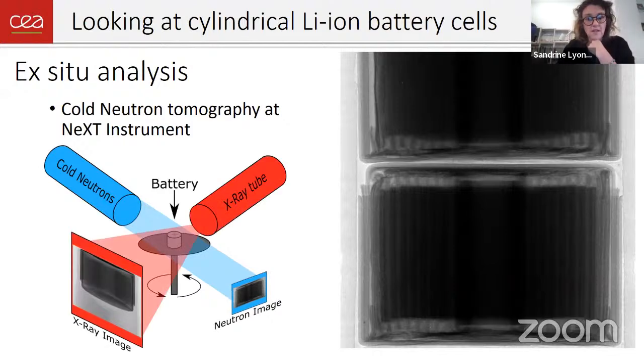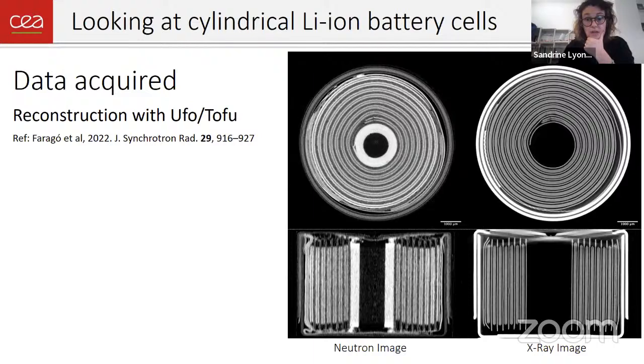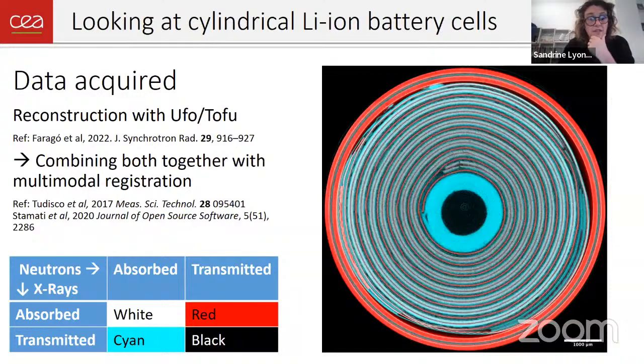What is nice on NeXT is they also have an X-ray tube, so you can also take the X-ray tomography on the very same cell without touching it. And this is nice because you get two sets of data, and the two beams are not sensitive to the same elements. X-rays will be very much absorbed by, in particular, the current collectors, while neutrons will be absorbed by lithium. And at the end, you can have this multimodal registration where you mix the two images, you align everything, and you get an image of your cell.